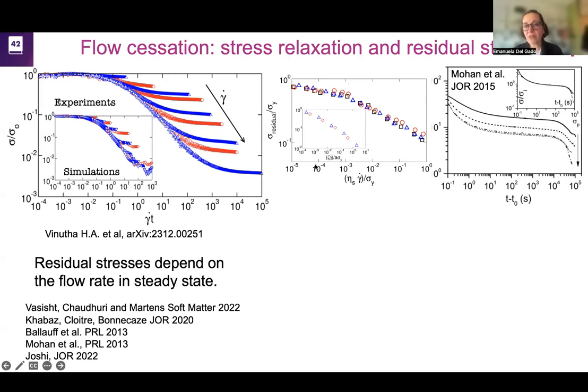And in fact, as you can see in this central plot, it depends on both the rate and, for example, the dissipation. Here, the experiments were done with different viscosities of the solvent. So you can see that, in fact, the viscous stress that was developed during the flow is what seems to control the final residual stresses. And in the inset, in these two plots, you have the same measurement, the same test done in a simulation in the same kind of jammed soft solid that I was showing you before.